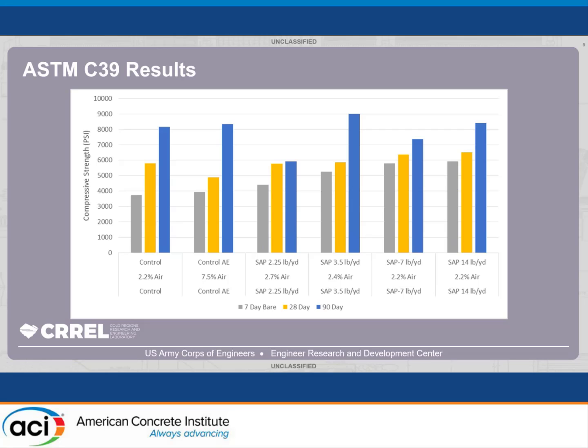So it's stronger than the control, even as we add more SAP. And in addition, our 28-day strengths were pretty comparable to the controls. As you can see, there's still a gain at the 90 days as well. The gray is the 7-day, the yellow is the 28-day, and you can see a pretty large growth at the 90-day.